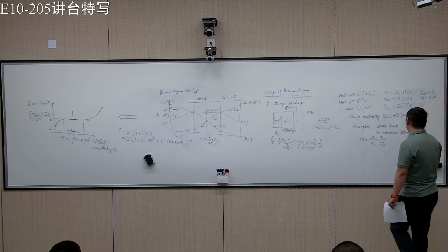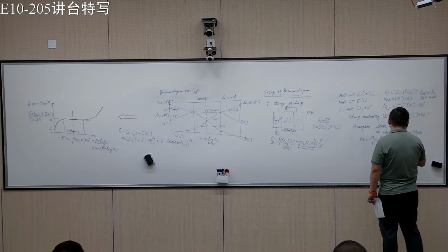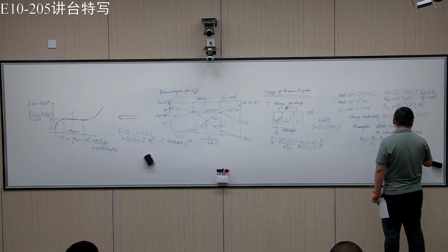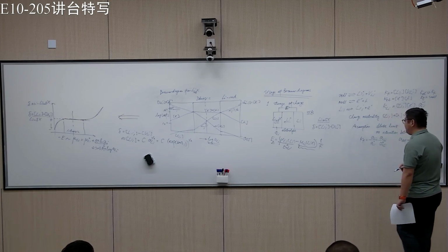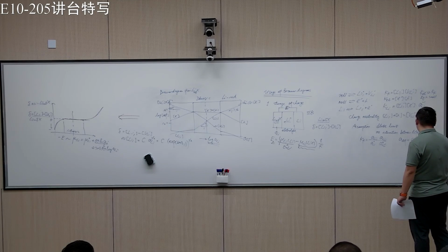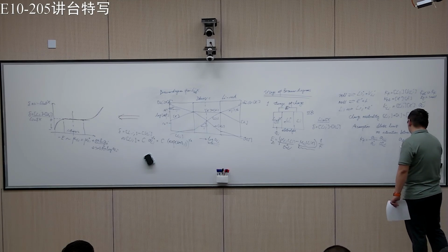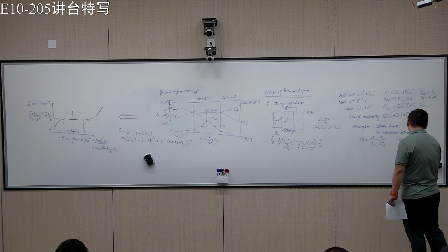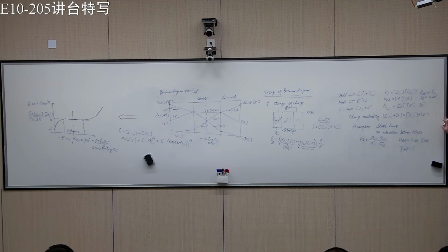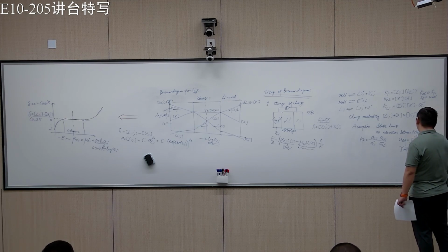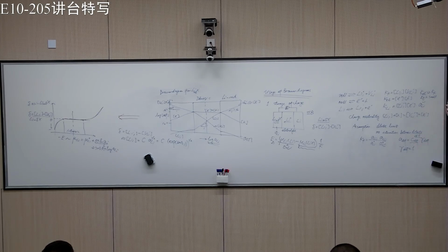So the assumption we make is basically the activity of any defect will be the same as the concentration. Of course, formally you write with activity coefficient, or we say this coefficient should be 1. So this is generally true when you have this much smaller than, so basically we have a very dilute system.